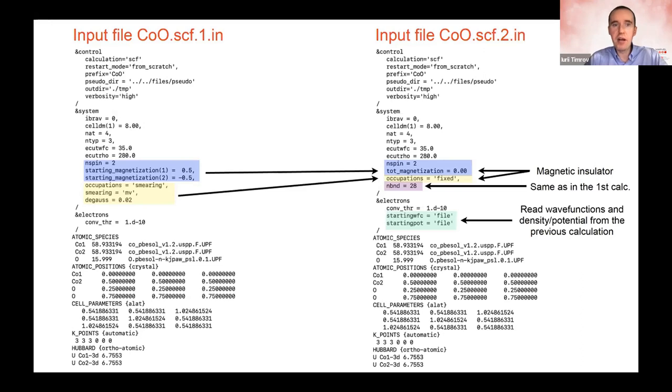And since you have an insulator, you don't really have a Fermi energy, you have a gap. You will see you have vanishing density of states at the Fermi level. And when you divide 1 by a very small number, you get infinity, so essentially a singularity. So we have a magnetic insulator, but we treat it as a fake metal, and this will explode our HP calculation. So that's why we need to do the second SCF calculation,